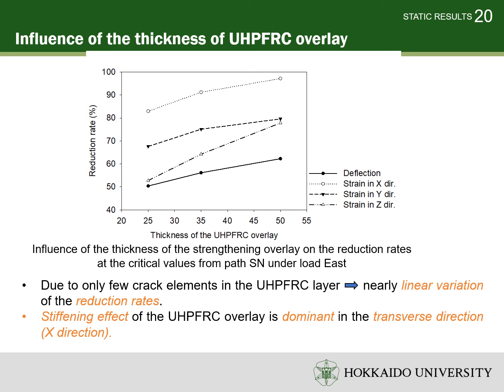For the model of 25 mm UHPFRC thickness under the load level of 100 kN, there are only a few crack elements on the top surface of UHPFRC. For the models with 35 and 50 mm of UHPFRC thickness, there is no occurrence of crack in the overlay. Therefore, the linear variations of the reduction rates are obtained. Considering the strain reduction rates along the midspan, the values in the X direction or transverse direction are always higher than those from the vertical and longitudinal directions. It means that the stiffening effect of UHPFRC overlays is dominant in the transverse direction.